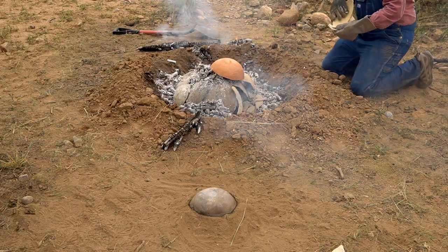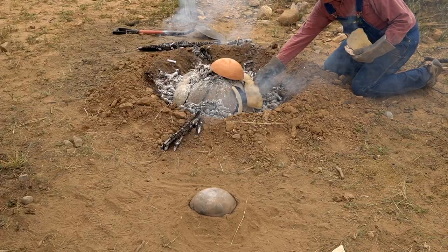I was afraid that if I just started throwing dirt on there, it would come right up in contact with the jar and make it all dark. When I was setting it all up, I had these cover sherds that I'd made. I left one out because I didn't have room for all of them in the firing. So I grabbed that unfired cover sherd, thinking it would at least keep the dirt off the pot. The problem was it was heating too quickly and just started popping and falling apart. So the cover sherd was going to bits while I was trying to smother it, and I wanted to get it smothered as quickly as possible because I didn't want any oxygen to get in there and start turning that black red. I stuck some smaller cover sherds in the hole, and I think I got it filled in so the dirt didn't come in on the pot.